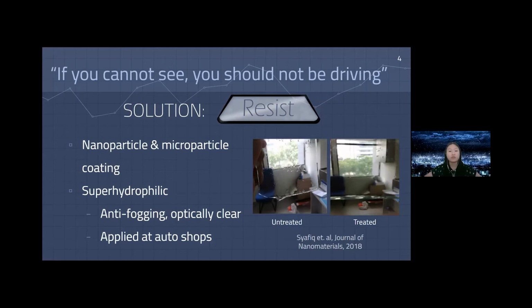And so this is where Resist comes in. We are creating a nanoparticle and microparticle coating that can be used on the interior of windshields to prevent fogging. And as you can see in the pictures to the right, it's optically clear and it's very effective at preventing water drops and any obstruction of your view. And so our customer is auto shops, where they can apply it for our end user of drivers.